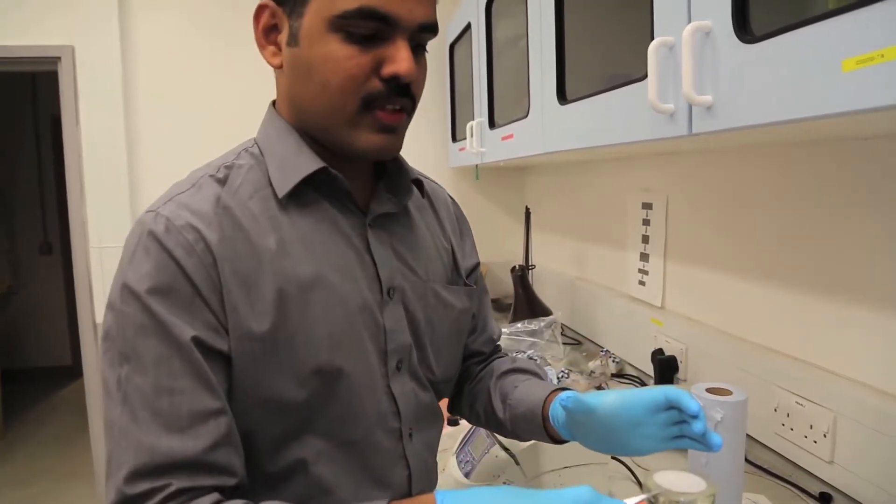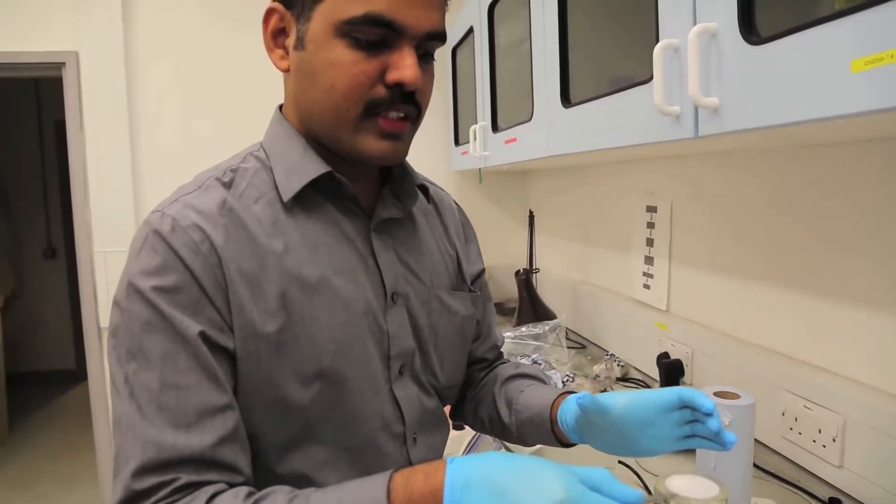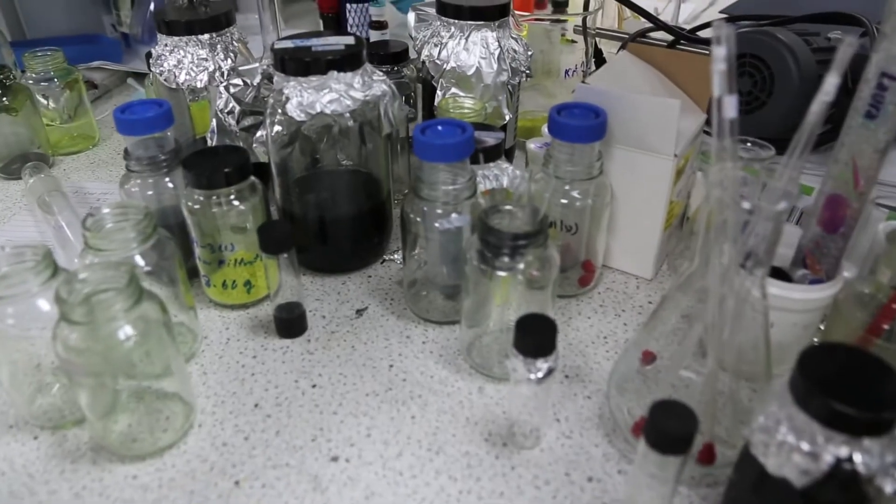So this is how we produce our graphene oxide membrane for our laboratory experiments. You use this kind of porous support material to deposit graphene oxide sheet to make a free standing membrane. So you use porous support there, then you pour graphene oxide solution over here.